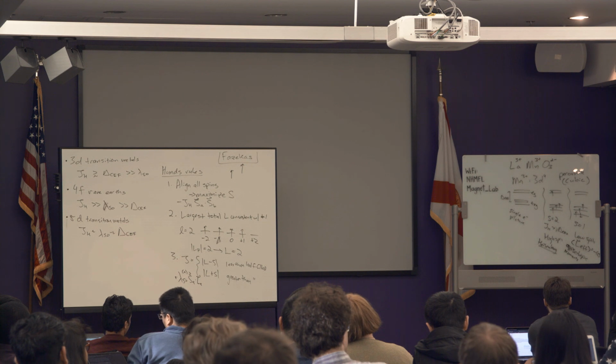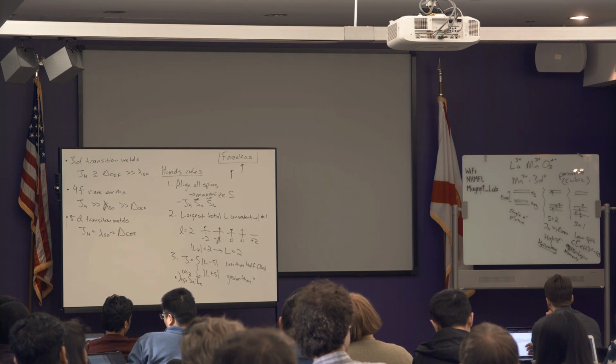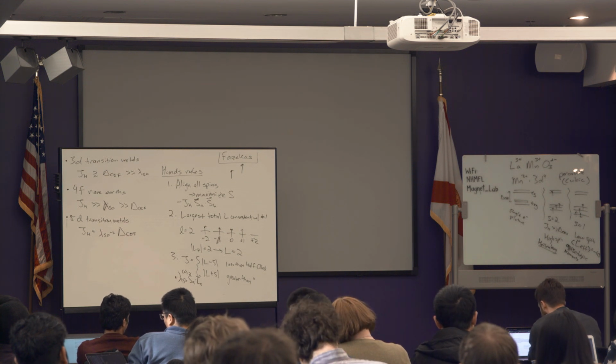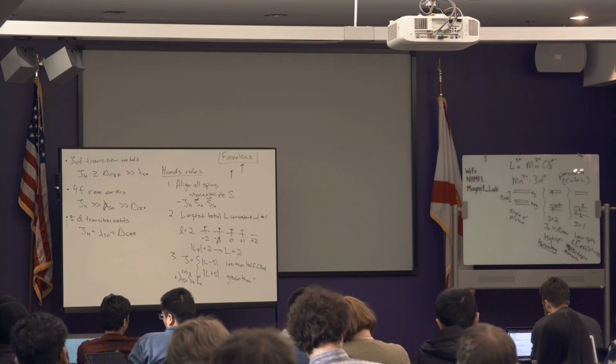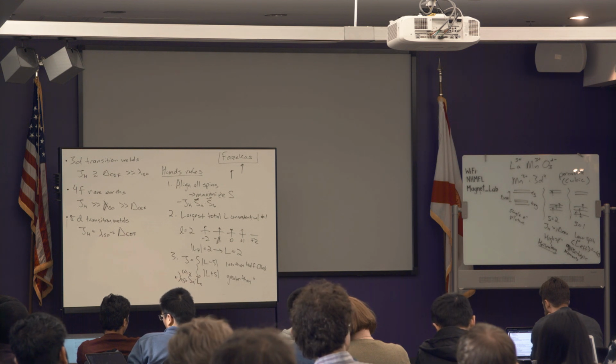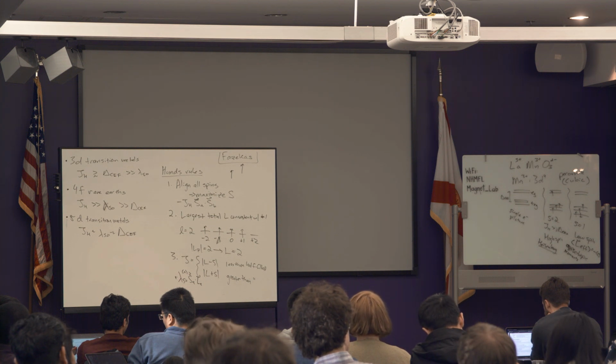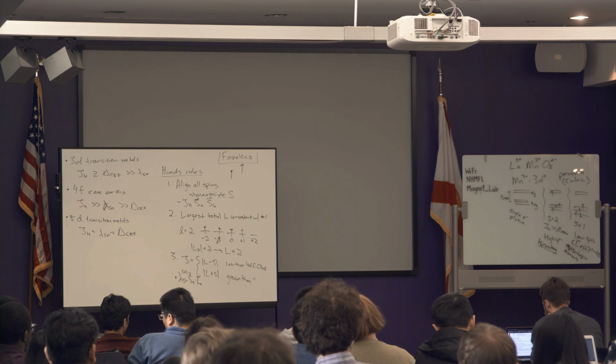And actually Colin showed you some data. So you measure it with inelastic neutron scattering. You can see these different local excitations. And so you can actually determine exactly what this configuration is. At this point, let's say we know that we have a doublet. So if you measure your magnetic susceptibility and you see you have some kind of magnetic susceptibility at low temperatures, you know you don't have a singlet. And so we have some J equals 4.